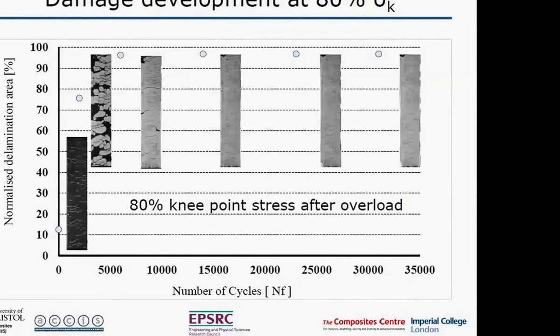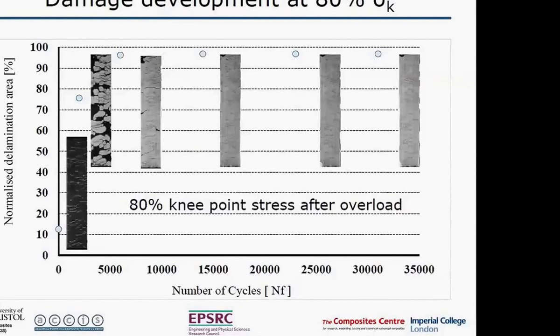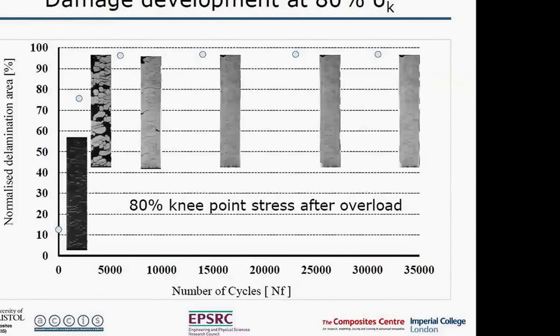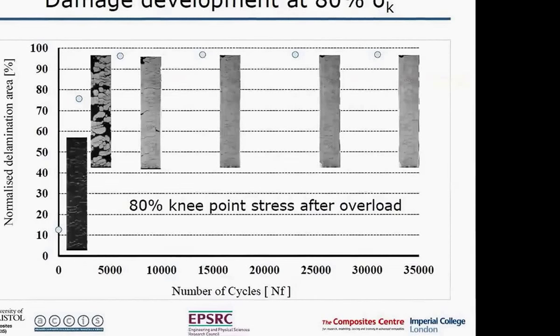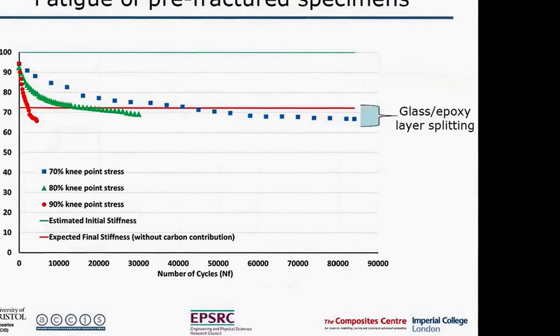And if you reduce it to 80%, it takes a few more, but still over 7,000 or 8,000 cycles, we're delaminating. Because we introduced that damage by initial overloading, it's a bit more susceptible and it does fail a bit more. But we can look at the overall summary here. This shows that at 70%, it goes out to quite a few cycles before it really completely delaminates.